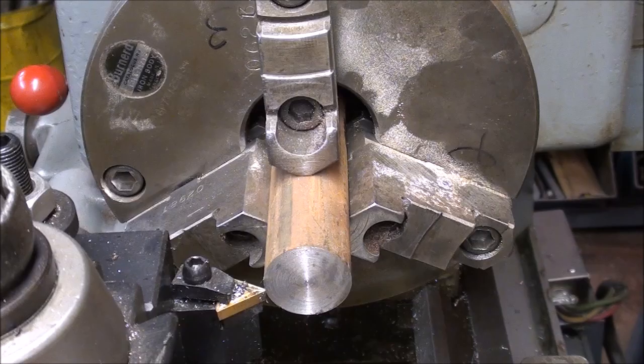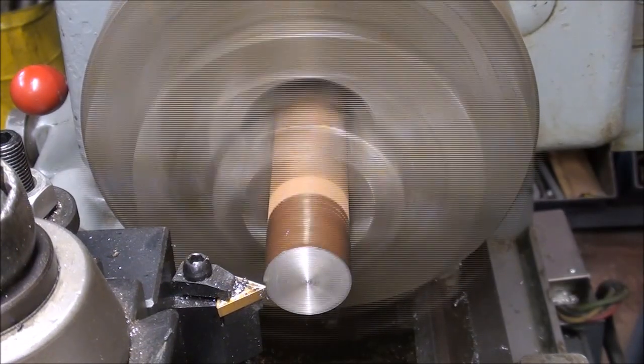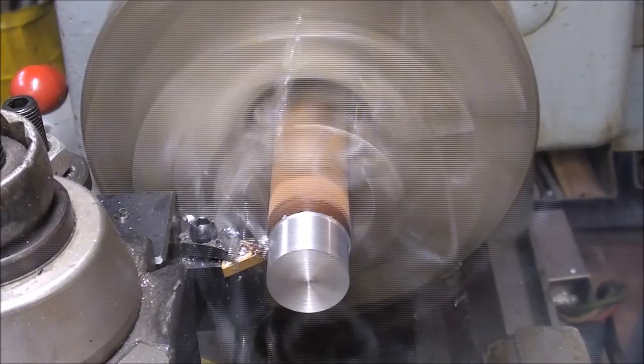This is the Leadloy 300, that is 12L14 steel. It really could be run at a much faster speed than this, but I want to keep it the same for all. You can see that the chips are quite a bit different — they're not long and stringy anymore. Very free machining. That was 50 thousandths; now I'll take a finishing pass of 10 thousandths.